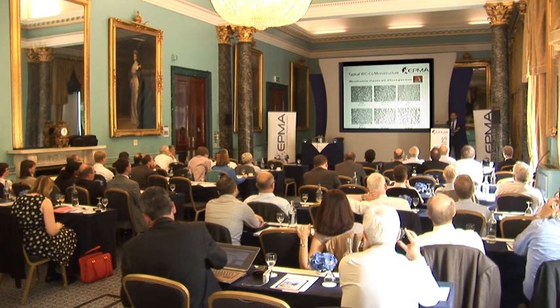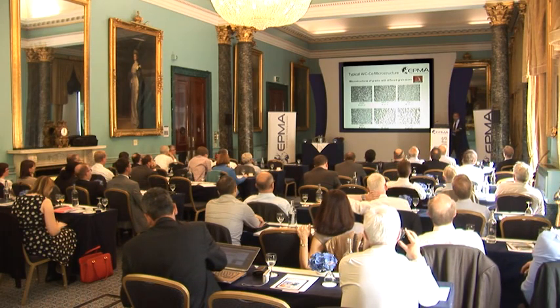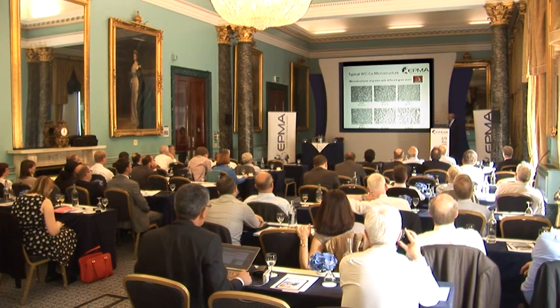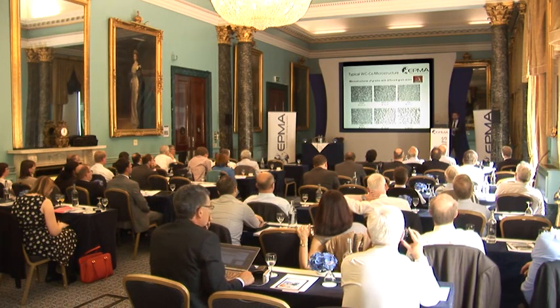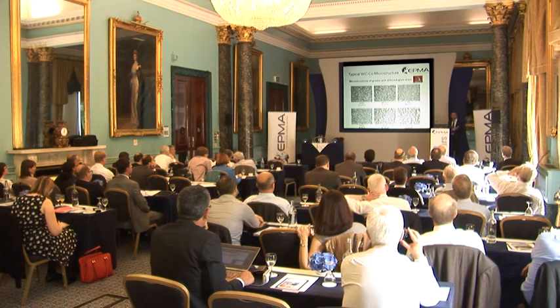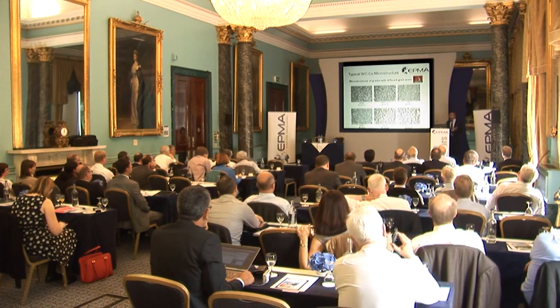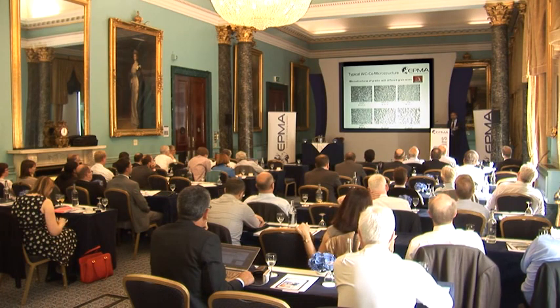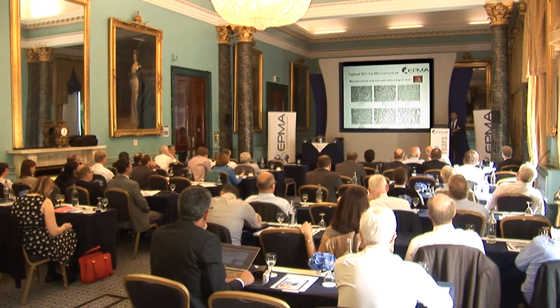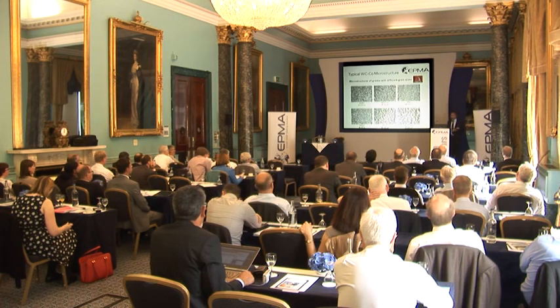A few words about trends. In 1989, the very fine-grained hard metal, less than 0.8 microns, was less than 10%. I remember talking to producers. They said, "Oh, forget it. It takes four times more time to produce powder with 0.8 microns compared with a normal 2.5 micron grain size." And they wanted me to pay double the amount for this material, which we couldn't pay. Today, submicron and smaller size WC is more than 50% of the total, especially because we use it for round tools, for drilling, reaming, etc.